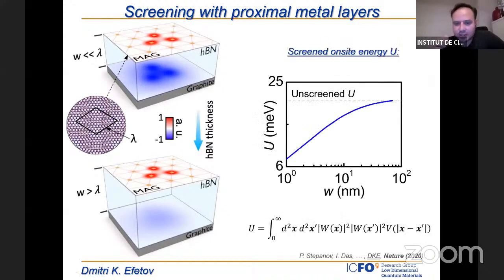And what the calculations are giving now, again by Leonid, is that this U parameter, as a function of the distance of the graphite gate to the magic angle graphene, can be treated as completely unscreened whenever the distance is more than 30 nanometers. Before this work came out, this was pretty much the thickness people used. But if you reduce the spacing to below 15 nanometers, you can see that U dramatically changes. I want to contrast these explanations with our findings.